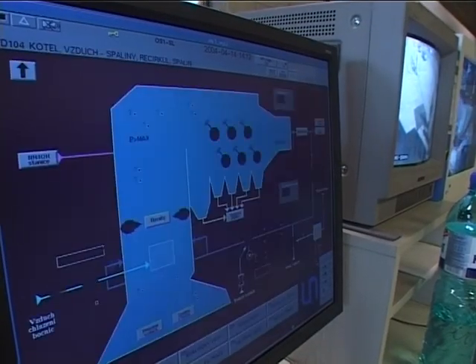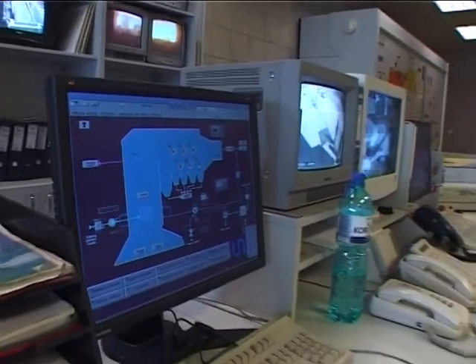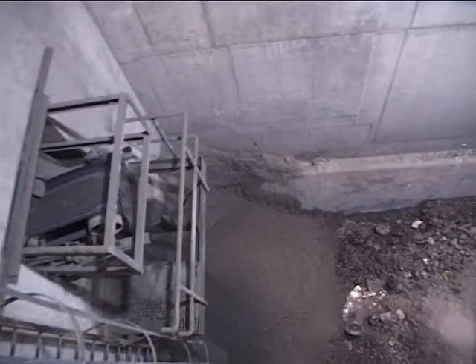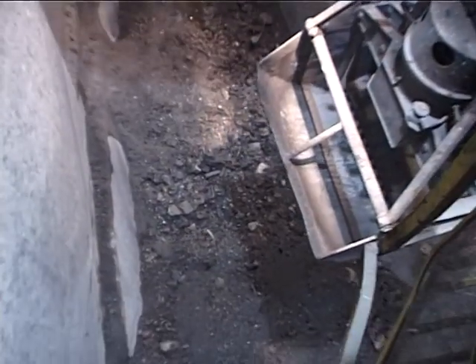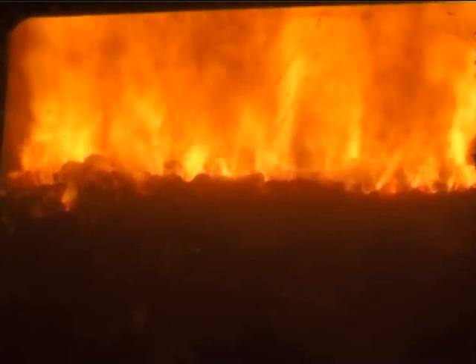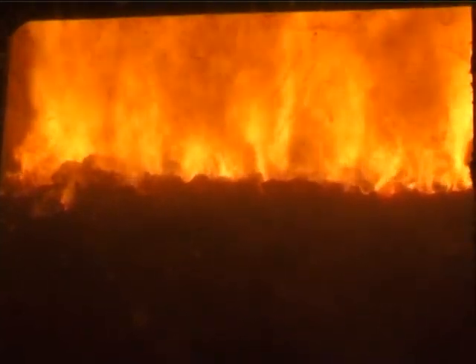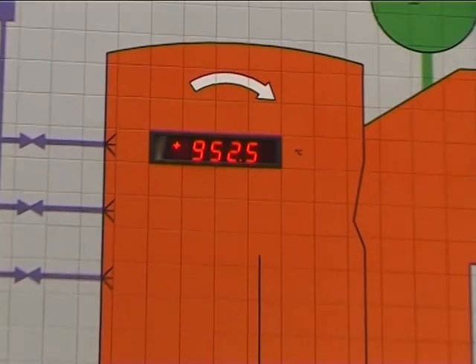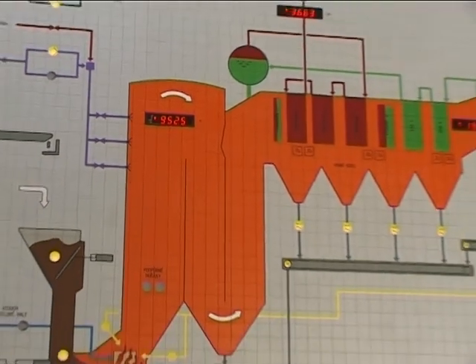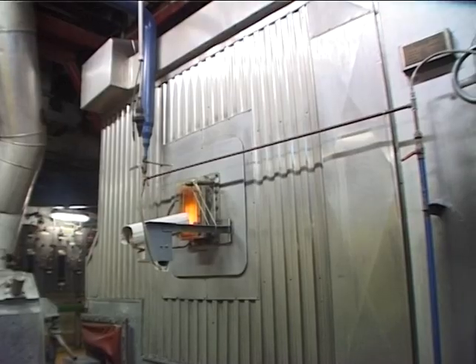The control system monitors individual combustion parameters and continually evaluates any deviations from the state required. This ensures complete combustion and the high quality of non-combustible cinder and fly ash residues. Burnt cinders contain a maximum of 1.5% carbon, which is proof of very good combustion. The combustion temperature on the grid varies according to performance from 900 to 1100 degrees C.